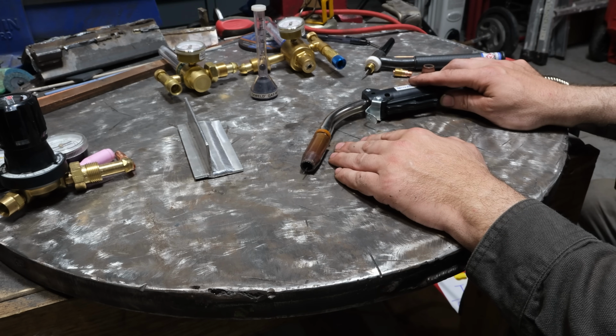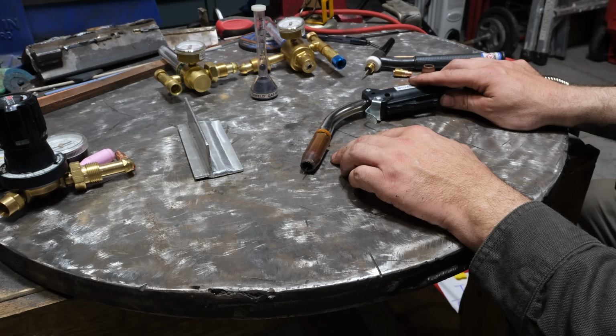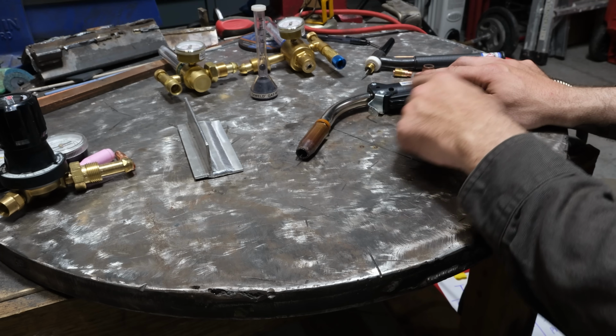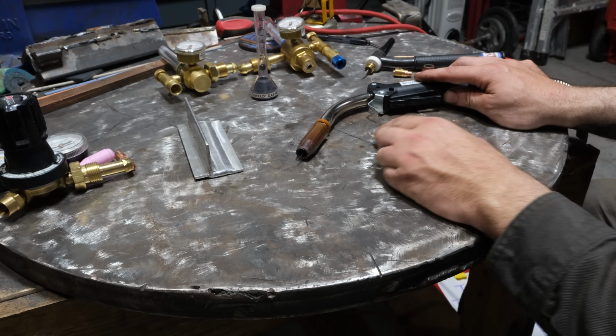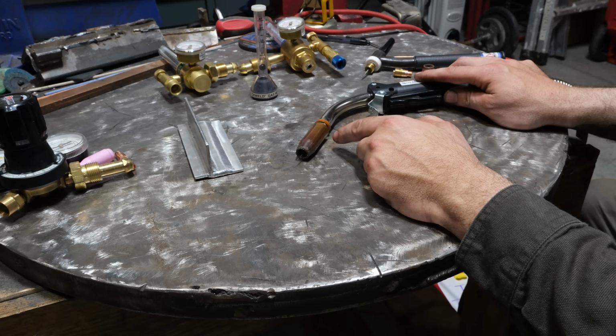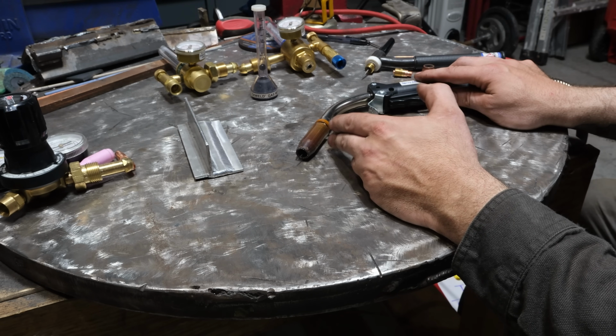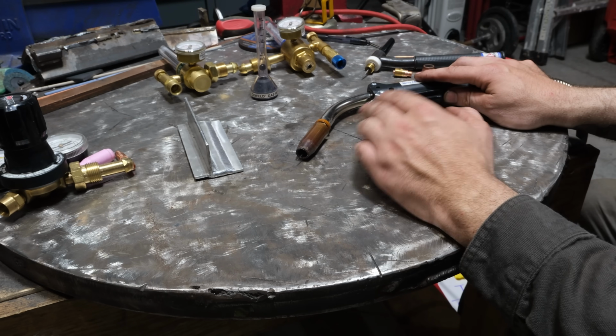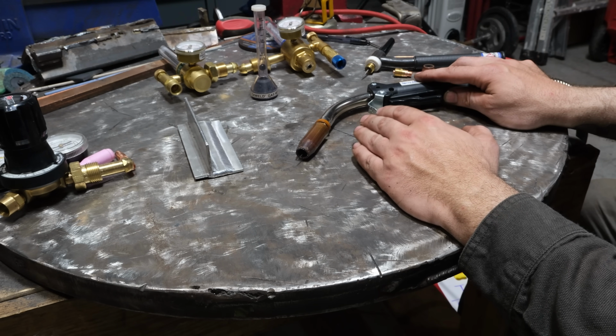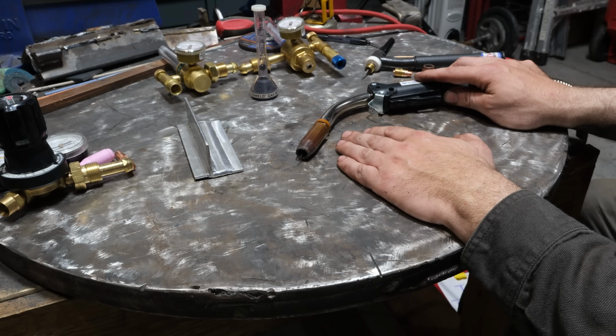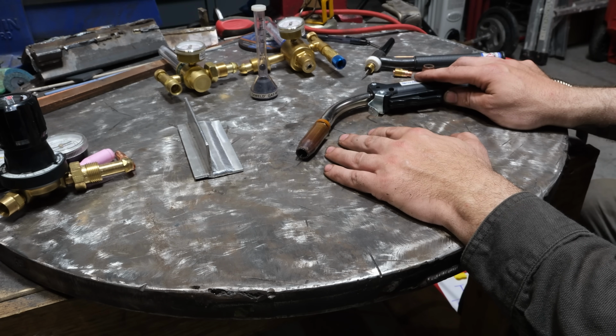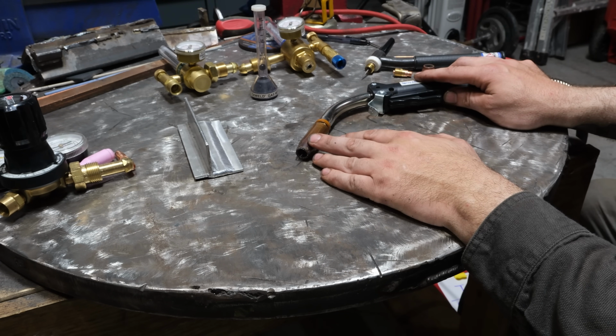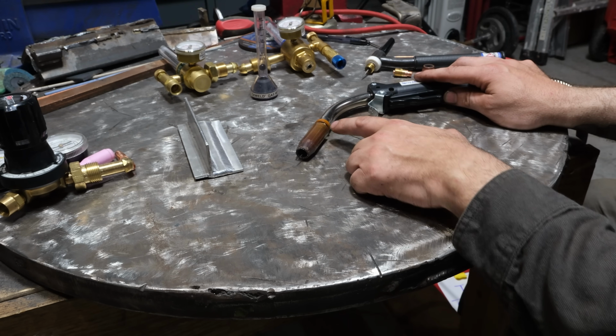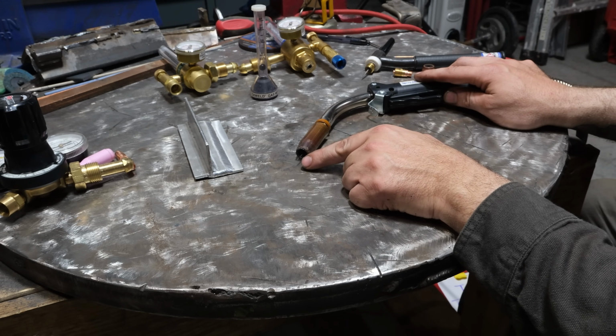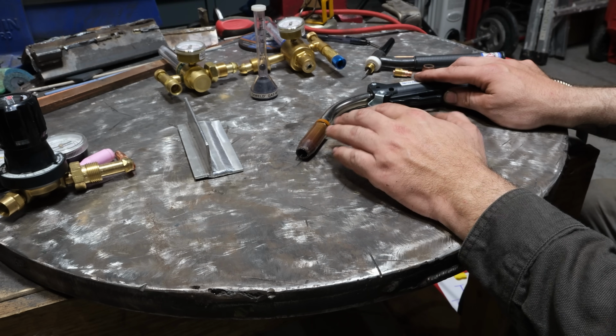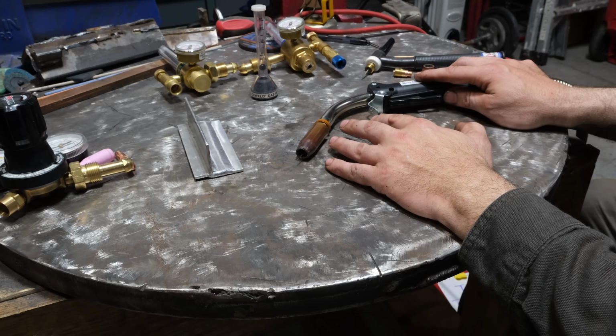If you have too low a pre-flow, what can happen is the start of your weld has porosity, because the gas has to make it all the way down the whip, out the nozzle, and to the molten pool before it reacts with oxygen. Well, if you adjust it higher, you may be able to run lower overall cubic feet an hour and still get acceptable welds. What can happen is that if you have no pre-flow or very low, you might have to set the cubic feet an hour on your flow meter higher just to get a faster push of shielding gas to prevent porosity at the start of a weld or during it. So that's something to consider as well.